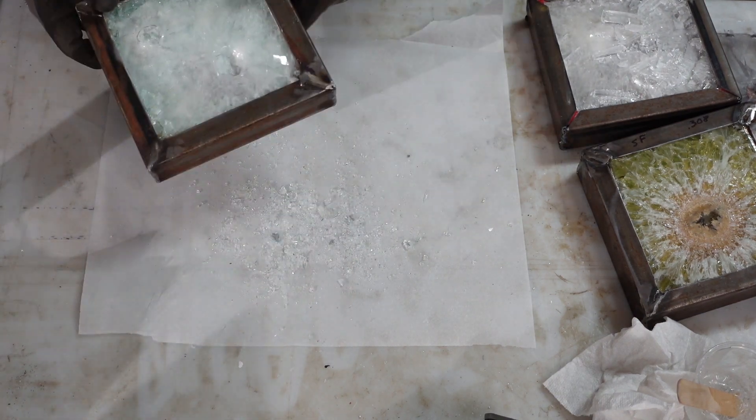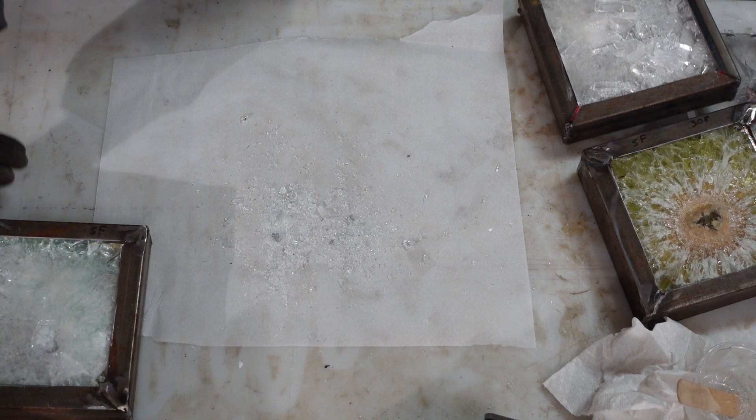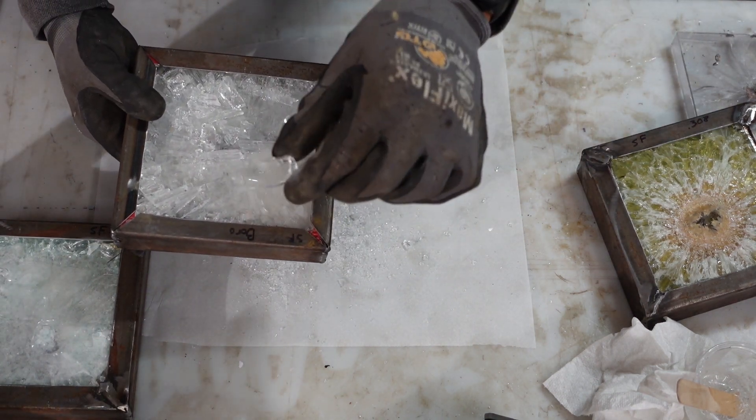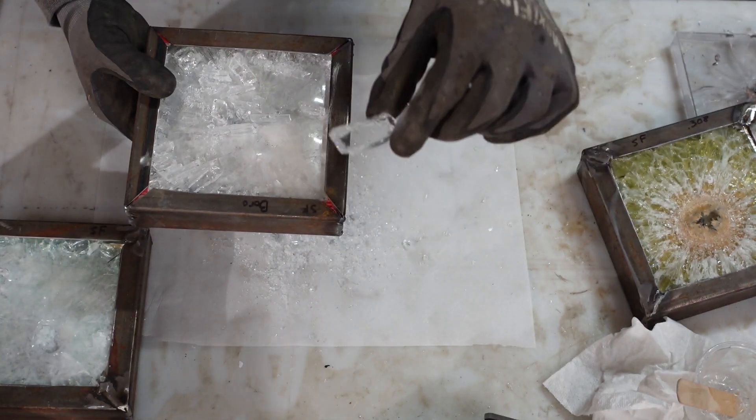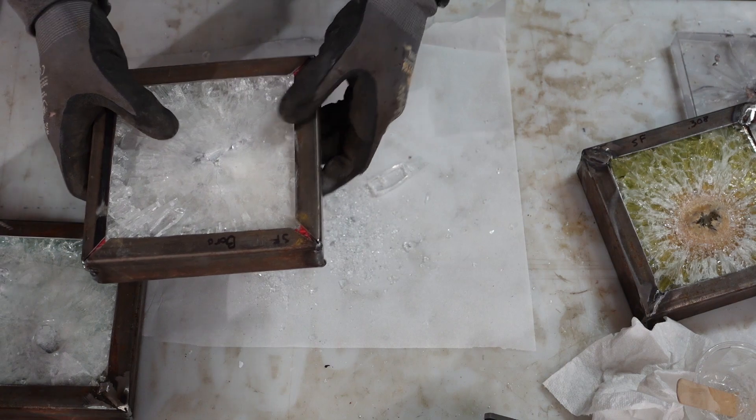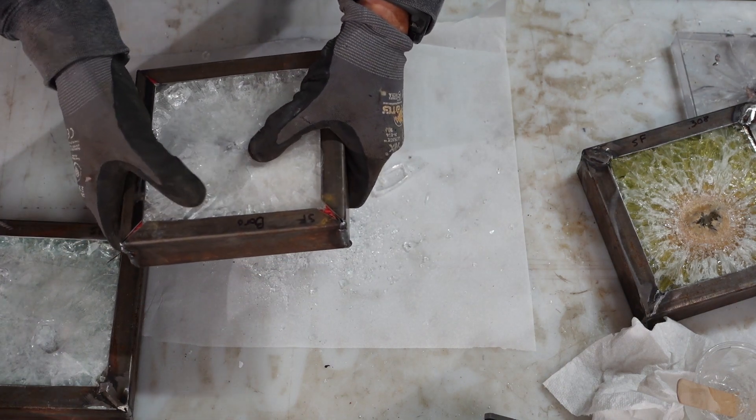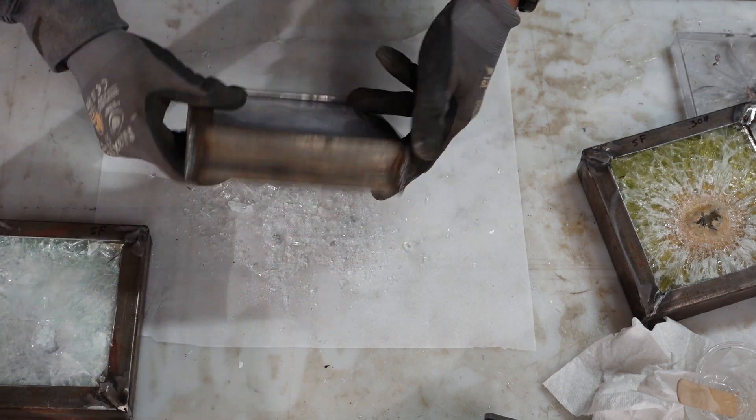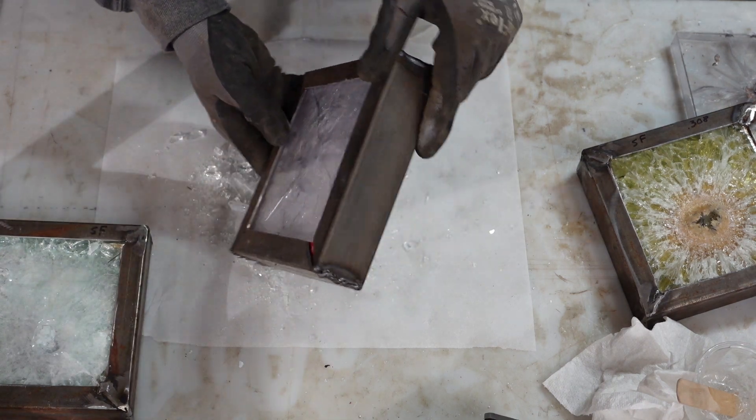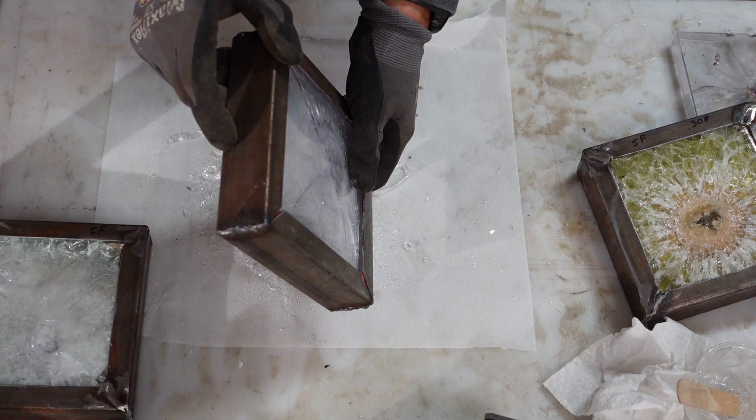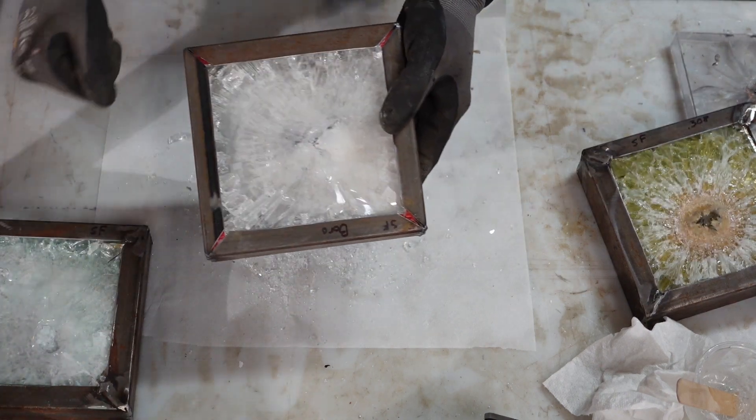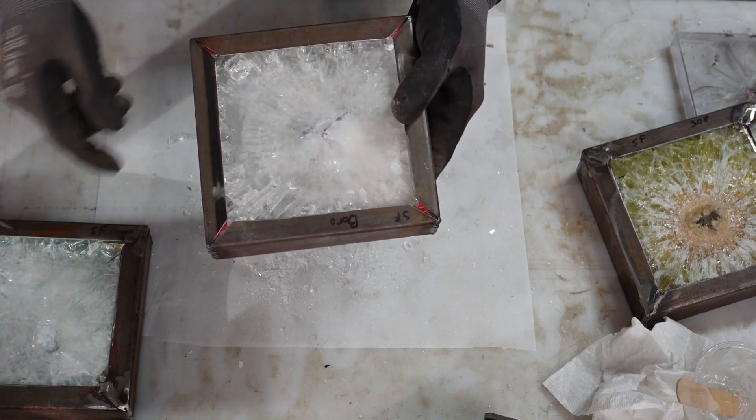I had nothing in front of these, so these were straight glass on all of these. No tint. I like to put usually a security tint or film on top just to hold it together. These had nothing. We were testing out the adhesion of certain materials in between. As you can see this UV resin is a flexible thing but it doesn't adhere as much. But we were able to stop the 7.62 by 39. Now the borosilicate glass, this stuff is clear, it is clear.